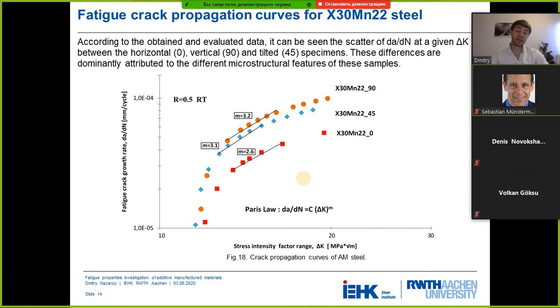By applying the data reduction technique, the crack propagation curves were constructed, and the scatter in the crack propagation curves is obviously seen, with slower crack propagation for horizontal specimens and the fastest crack propagation for vertical specimens. Tilted specimens showed results close to the vertical specimens, but the crack propagated in an intermediate fashion.